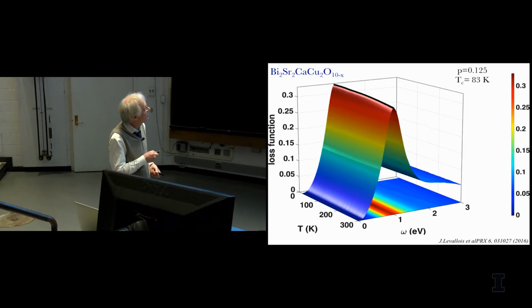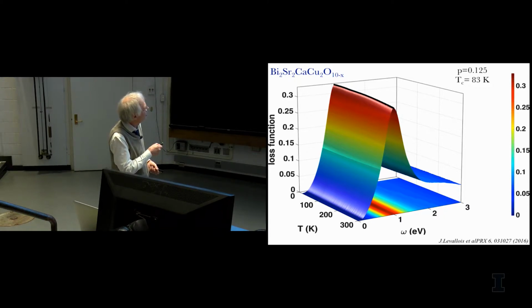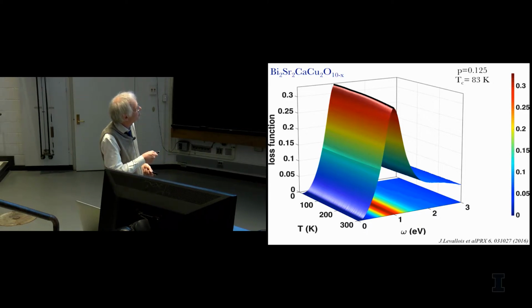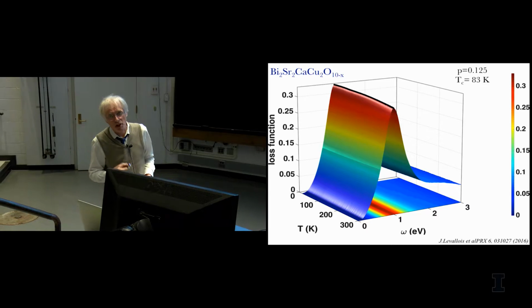Here you're looking at 300 spectra for 300 different temperatures. Sorry, it's 280. So we start at 10 Kelvin approximately. You go to 290 Kelvin or 300 Kelvin, I forgot. And every Kelvin there's a spectrum. This is such a loss function, from 0 to 3 electron volt. It has a peak at the plasma frequency.